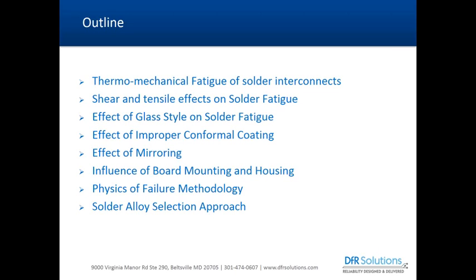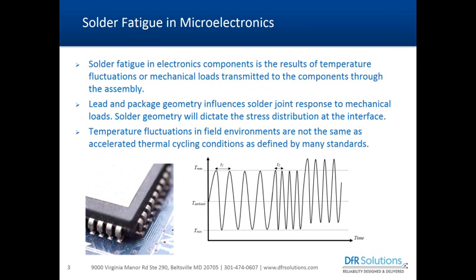I have a Russian accent — I'm originally from Ukraine. For those not familiar with solder fatigue in electronic assemblies, we're going to discuss primarily thermomechanical fatigue of solder interconnects. Unlike vibration-induced fatigue, thermomechanical fatigue is mainly a low cycle fatigue mechanism, while vibration-induced fatigue is usually high cycle fatigue. They do interact, but in high reliability applications thermomechanical fatigue dominates.